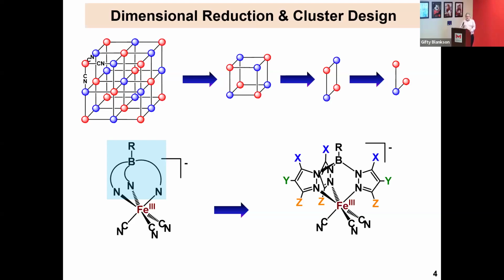The idea there is you simultaneously tune the steric properties, that is the size of the ligand, and the electronic properties, that is, does it serve as a donor or acceptor in a Lewis acid base. And by changing primarily those positions down there, the so-called 3 positions labeled Z, you can change how the cyanides bridge to adjacent metal centers, and you can control that from anywhere from 1 to 4, depending on the metal ion and number of cyanides present.